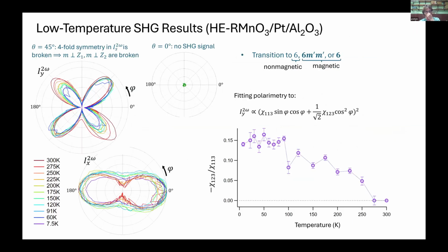Okay, but this is the interesting bit. What happens when we cool down? We do see a phase transition around 275 Kelvin. We see a symmetry breaking. These 2 lobes in the Y polarization shrink, and this indicates that we've broken the mirror planes perpendicular to the Z1 and Z2 axes. Now, what is responsible for this could be a structural transition, so something in the polar part, where you literally break these mirror planes, or a symmetry breaking in the magnetic phase transition. So you can have a few different point groups.